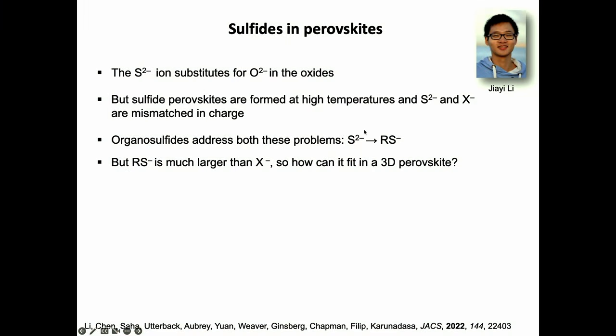That means a sulfide where we have stuck an organic group to one end of it. And this changes the charge to 1-, so now it has the same charge as a halide. Organosulfides are used by biologists and organic chemists. They go into solution, go into water, and they work at room temperature. Except that if you put an organic group on sulfur, you can imagine that it's much bigger than a halide. So how is it going to fit into the halide site in a perovskite structure?